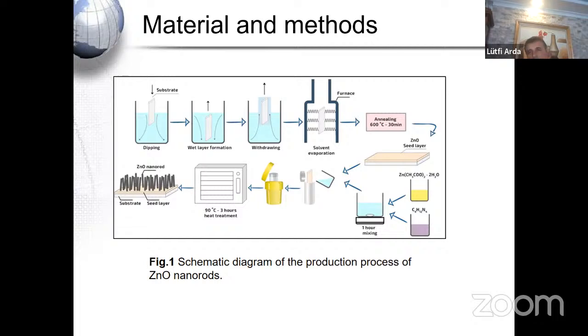Zinc oxide nanorods were produced at different reaction times of 3 hours, 4 hours, 5 hours at 90 degrees Celsius, and different reaction temperatures of 90 degrees Celsius, 120 degrees Celsius, 150 degrees Celsius for 3 hours. Finally, deionized water was used to wash the substrate, which was dried in a vacuum furnace at 60 degrees Celsius overnight. As a result, we get nanorods on the zinc oxide thin films.